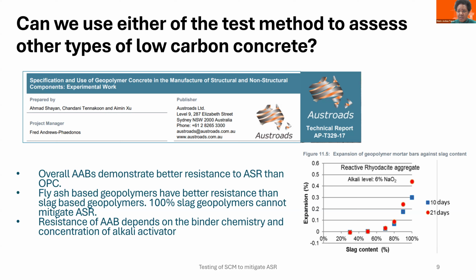Not surprising, because basically with very high levels of alkali, you're almost pushing the required silicate in the system to a higher level to be able to mitigate. So in fact, if you look at the plot on the right, if your slag geopolymer is about 100%, no fly ash at all, it cannot mitigate ASR. With this particular level of alkali, the 6% sodium oxide equivalent, about 10 times what you have in your cement. Again, the resistance of alkali-activated binder depends on the binder chemistry and the concentration of the alkali activator.